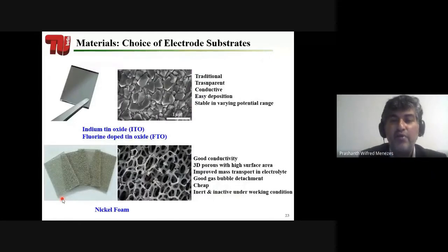Okay, now let's imagine that we have synthesized some powder. Let's say you did an experiment and then you got some powder. Now we need to deposit that powder on some electrodes to use it as an anode or cathode. The great choices for such electrode substrates are ITO or FTO or nickel foam. Why? Because ITO, which is called indium tin oxide, is very traditional. It has been used for many, many electrochemical purposes as a substrate. It is transparent and conductive. Any powder you can deposit very easily on it. And it is also very stable in a varying potential range. You can apply any potential within this water splitting system, and it is stable.